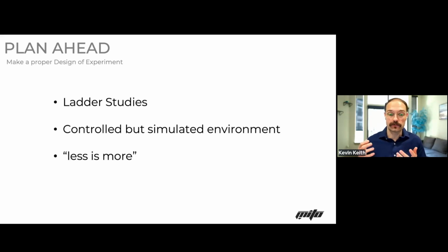And usually, I suggest that you do this in a controlled but simulated manufacturing environment, because in my experience talking with my customers, the times that they have tried graphene and have been successful at doing a really good design of experiment, when they scaled from a benchtop system, they didn't really correlate it to the production method. That's because it was in a very controlled environment, and when you go into production, there's more entropy and chaos involved than what you can do within a fume hood.